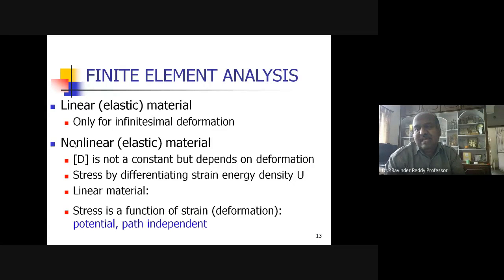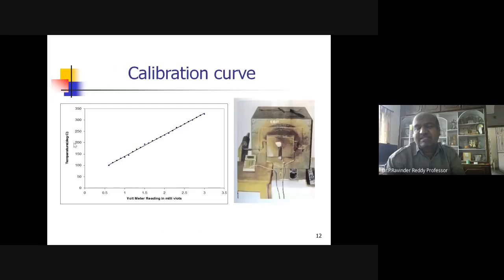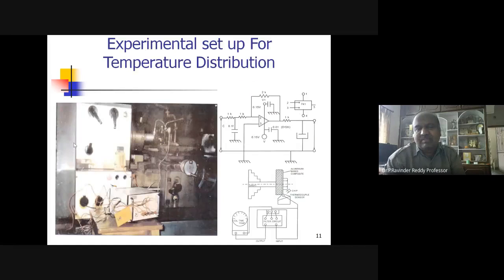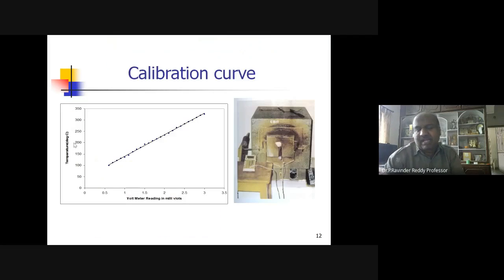Because when we do the experiments, one observation you can make is that there is going to be rubbing, there is going to be interaction between the chip, tool and work. When you measure with thermocouples, because these are contact type, we can have 3 or 4 thermocouples located in different places. So if 1 or 2 break, the others will have the temperature, so that we can take the average temperatures wherever we are measuring, because this is not a non-contact type, it's a contact type.